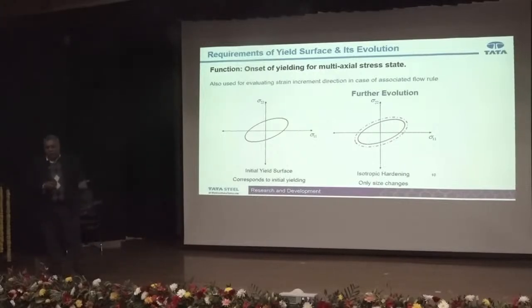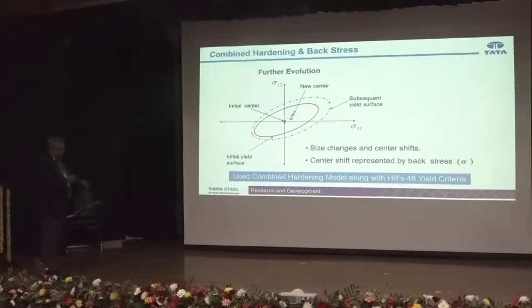However, the reality is not like that. The Bauschinger effect is a well-known phenomenon, right? The yield stress is actually lower. So it's not the correct representation, but it is very simple. 95% of the simulations in the industry actually use this, and therefore it is one of the reasons the accuracy is not there. A little bit more complicated, you say it doesn't only increase in size, but it also translates.